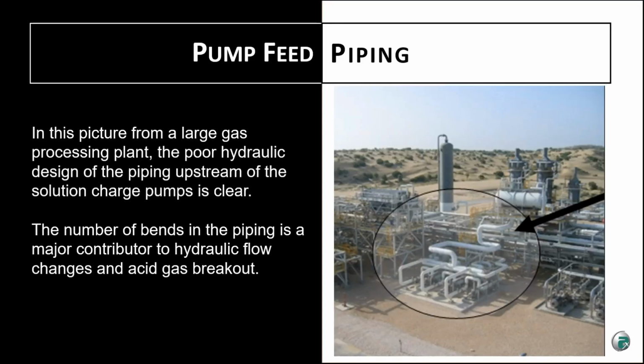This picture from a large gas plant shows the very poor hydraulic design of the piping upstream of the solution charge pumps. It's quite clear that there are far too many bends in the piping, and they were a major contributor to hydraulic flow changes and acid gas breakout that caused severe corrosion at this location in the plant.